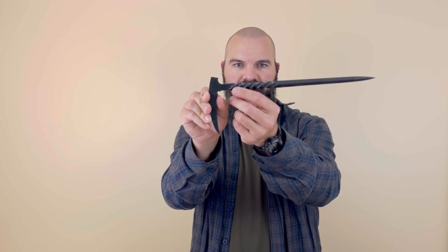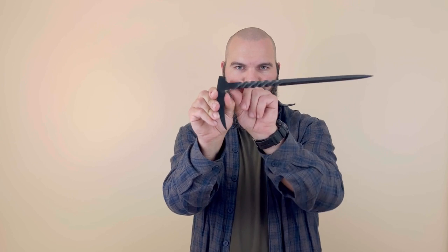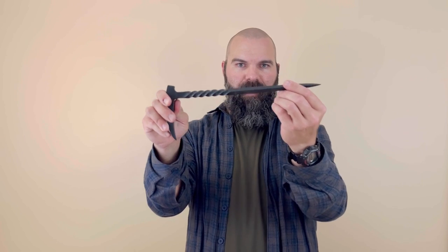So then we took the water jet cut blanks of 1075 steel and worked with our blacksmith. He's a wonderful blacksmith who was able to forge and twist, getting about 6 twists and then a partial twist to go from square cross section to diamond cross section. Then there was freehand grinding on a belt grinder for this portion here, heat treating, and then more grinding and hand file work to break the corners here.